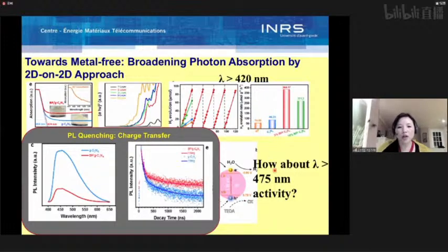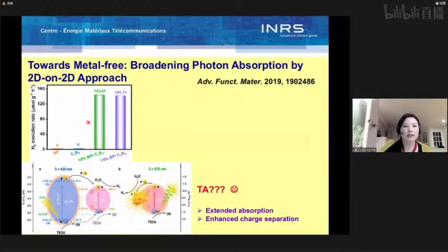But how about longer wavelength activity? Remember, one reason we want to combine BP with C3N4 is to extend light absorption. So we tested photocatalytic behavior under longer than 475 nanometer irradiation. At this irradiation, basically C3N4 doesn't absorb, only BP absorbs. And for this longer wavelength irradiation, we also observed a large increase of hydrogen generation as compared to pure BP and pure C3N4.